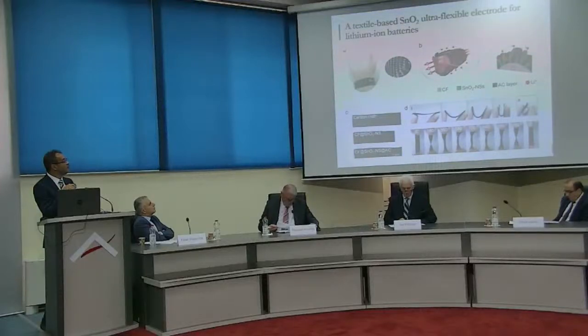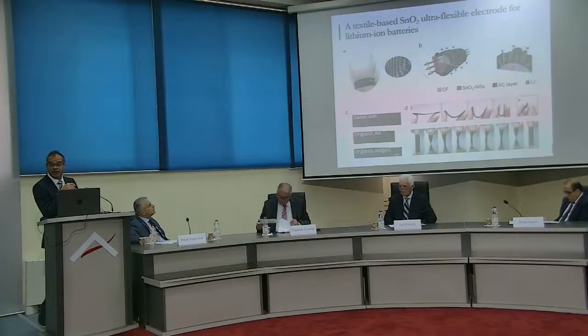We did even print it on textile, cotton textile, and we coated it with some layers, and it was washable. So we were able to wash this textile 50 times in the normal laundry wash, and it survived it. The battery was still cycling.